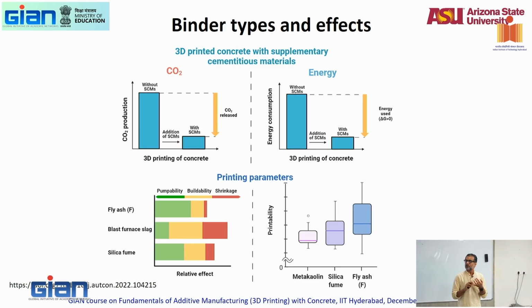So a few things that'll be handy. And let's do some thought exercises here. I give you a bunch of different cement replacements. Let's assume that you have all the cement replacement materials that you commonly have, okay? And if I tell you, you can't change the water content in your mix, but I want the yield stress to be dropped. I want a lower yield stress. Your water content has to be the same. I want a lower yield stress. I'm giving you cement, fly ash, silica fume, slag. What material will you use? Fly ash. Why?